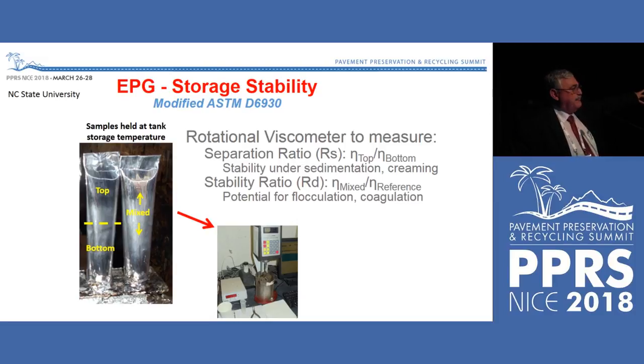We're looking at the top and bottom to see if we get sedimentation, using the toothpaste tubes we typically use for polymer modified materials. Also looking at what materials look like after a period of aging in the oven versus before on average, to see if we're getting any flocculation of materials. And so it's both sedimentation and flocculation, coagulation during storage we're after.